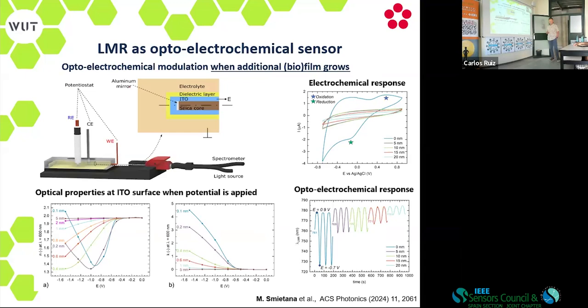So at that time, with ALD, we deposited a very thin material on top of the ITO just to simulate the conditions that take place when the biosensing processes are going. So you can see that when negative potential is applied to the electrode, the refractive index of this thin surface of the ITO drops significantly and then increases. But it drops significantly differently depending on the thickness of the film that is formed on the surface. So this is a great biosensing principle.